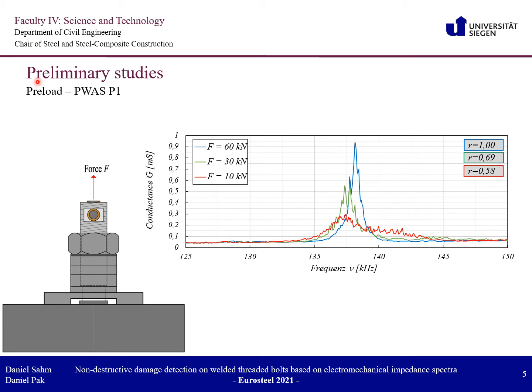The increasing amplitudes correlate with increasing preload. Furthermore, a slight shift of the resonance into a higher frequency range can be observed with increasing preload. This could be due to the fact that the eigenmodes shift into a higher frequency range with increasing preload.